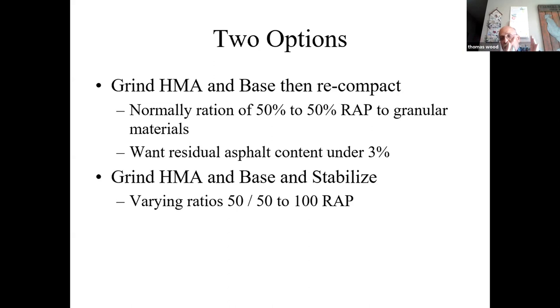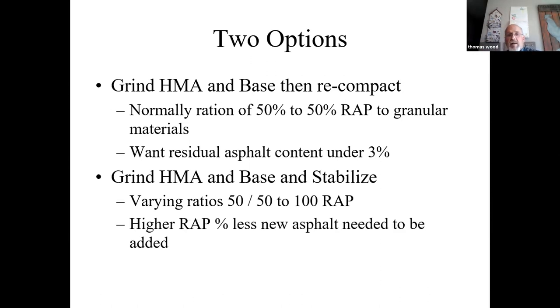And if you go 50-50, you have to add X amount of emulsion or foamed asphalt to meet the stability requirements. If you go 90-10, the amount of emulsion or foamed asphalt you have to put in goes down dramatically to meet the same criteria. So you end up saving yourself money and getting the same process.